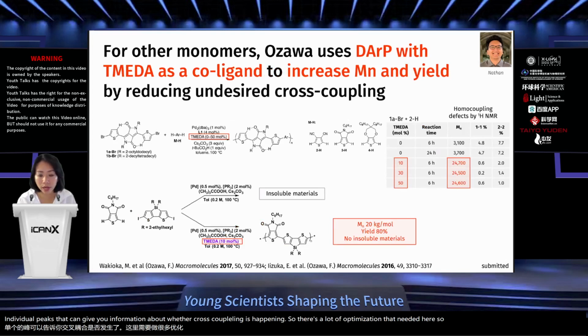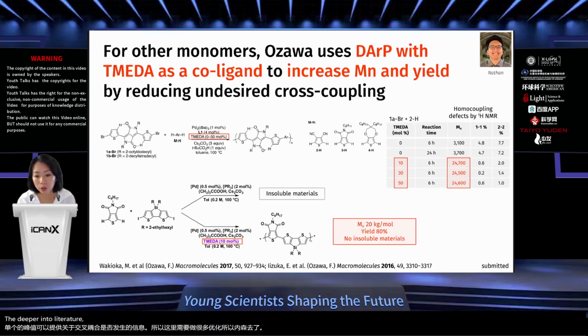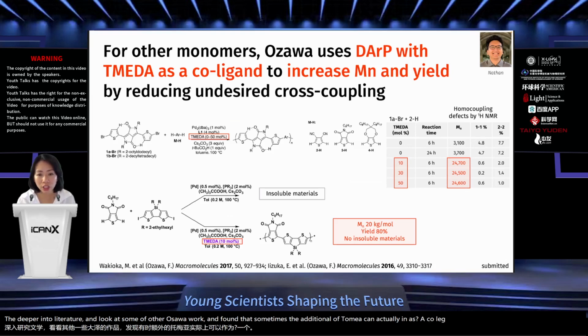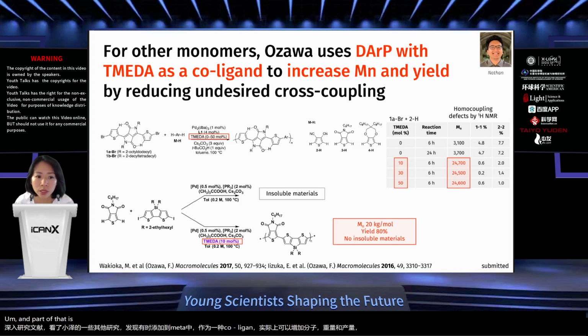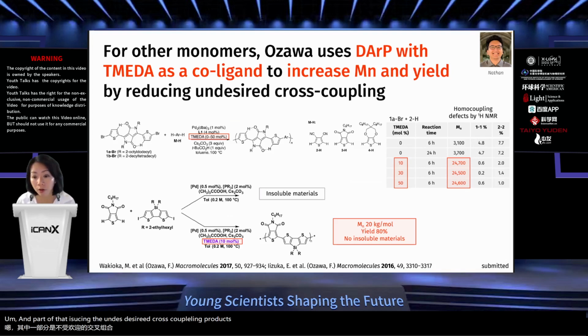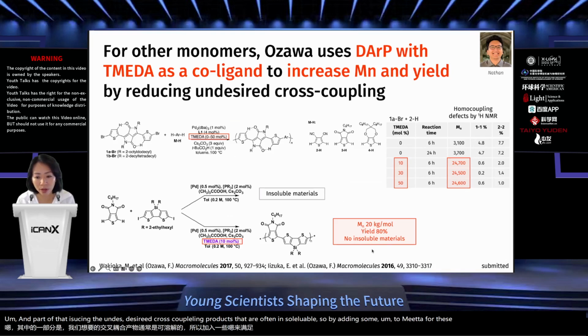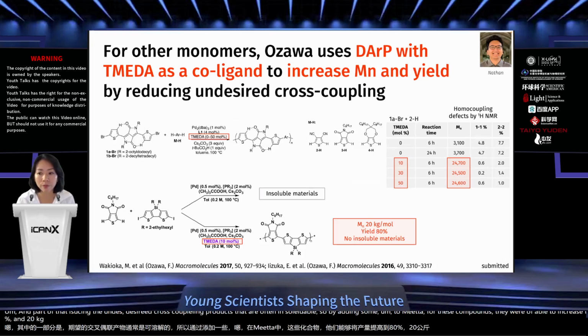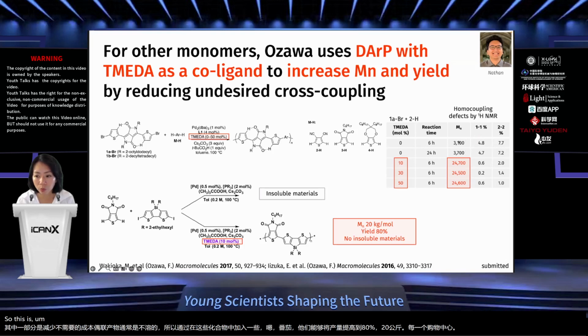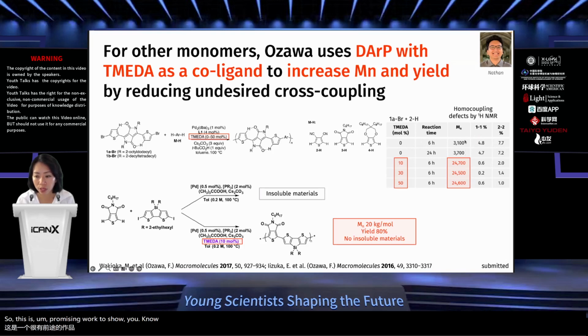So Nathan went and dug deeper into literature and looked at some of Ozawa's other work and found that sometimes the addition of TMEDA, as a co-ligand, can actually increase the molecular weight and yield. And part of that is reducing the undesired cross-coupling products that are often insoluble. So by adding some TMEDA for these compounds, they were able to increase their yield up to 80% and 20 kilograms per mole. So this is promising work to show, without TMEDA, they get around 3K, and that's actually quite similar to what we got.